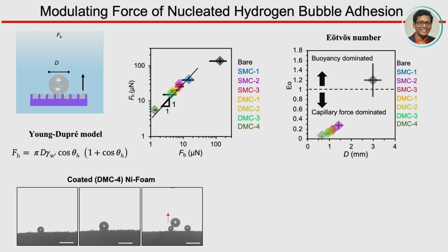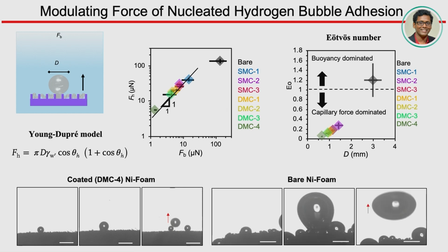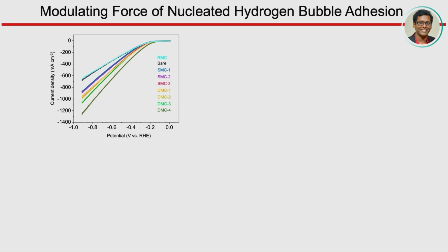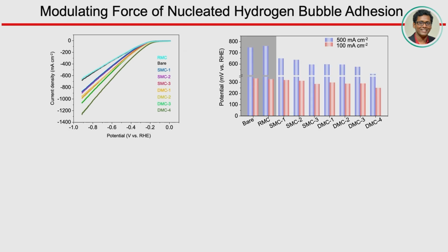Because of this, you can see the coated foam, the bubbles can release way earlier relative to the bare nickel foam. For the bare nickel foam, the bubble size is much bigger, around 3.5 millimeter, whereas this one is in the micron range, right? Because of that, you can see this LSV is improved. The current density at a given potential is very high, improved significantly. Not only that, the overpotential is also improved with respect to the bare and the reactive multilayer coating.